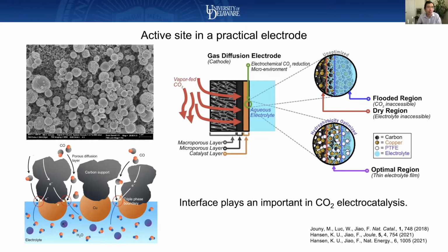And you can see they just randomly stick on the surface, and it's not just the catalyst itself. If you zoom in a little bit, you will find that where the reaction occurs is actually at the interface where the catalyst surface is properly wetted, and the gas reactant can rapidly diffuse to the active site. We typically call this the triple phase boundary, but technically even this is still not right because it doesn't capture another level of complexity in a realistic electrode.